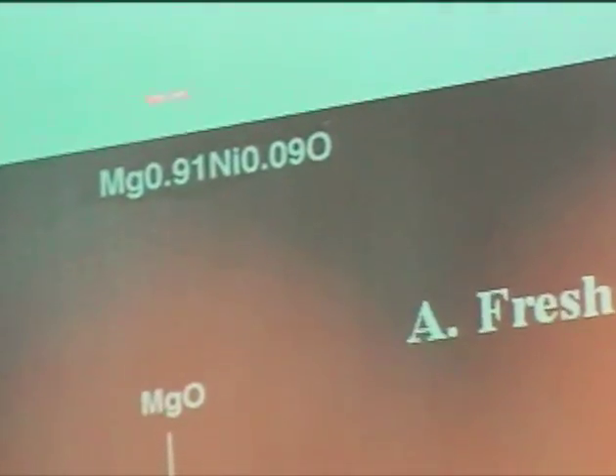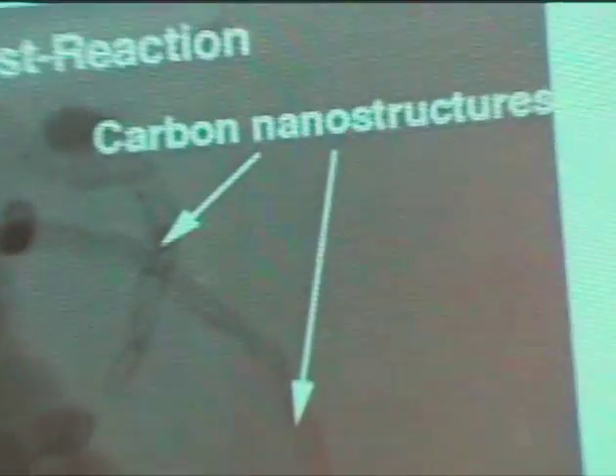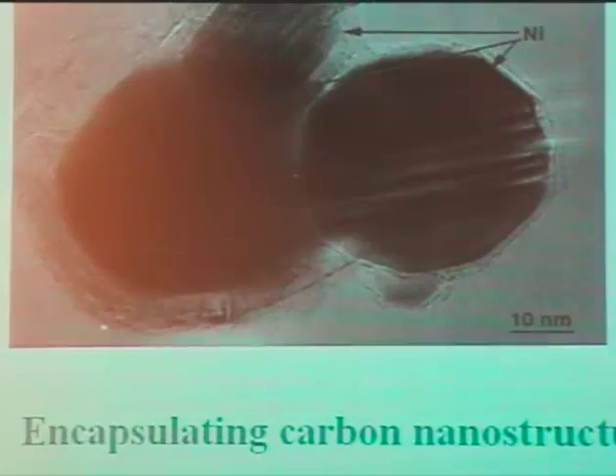Without the promoter, we have some TEM images here for the fresh and the spent. And even because we do that pre-reduction step, we're generating some nickel metal, maybe like 30 nanometer diameter particles. And then after being spent, of course the nickel's there, it's sintering a little bit. You see a little bit of carbon nanostructures showing up. And again, without the promoter, looking at the spent material, the carbon nanofilaments literally encapsulate the nickel particles.